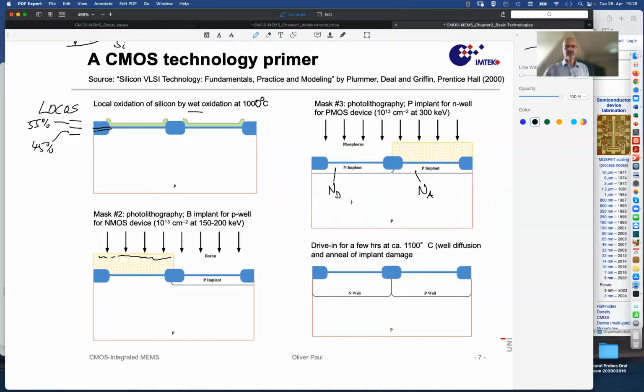And from what I see here, actually, I have to conclude that the P substrate was very weakly doped. If it had already been heavily doped, then this additional doping wouldn't make any change. So it must be a very weakly doped silicon. It says P, but it's weakly P. So that when you inject some P, and even after that P has been distributed over a bigger thickness, what you have injected determines essentially the dopant concentration in this well region, this P well or this N well region.